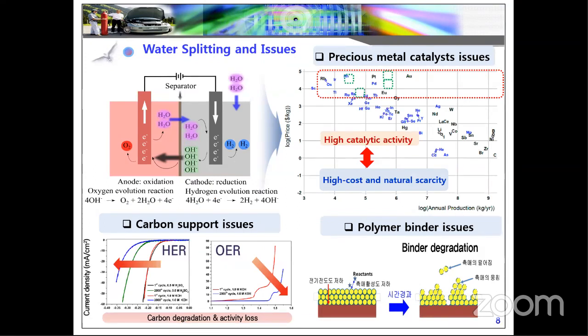Water splitting and issues. What are the current issues? What is the mechanism in water splitting? You can see the anodic part. At the anode, oxidation usually happens, and at the cathodic part, hydrogen is released, while at the anode, oxygen is released. The commercial anodic water splitting materials are iridium oxide or ruthenium oxide, and commercially the hydrogen evolution reaction happens on platinum and carbon based materials.